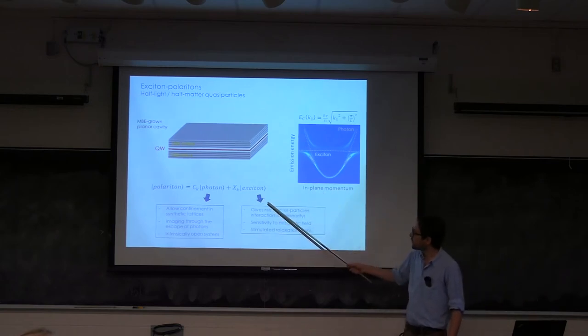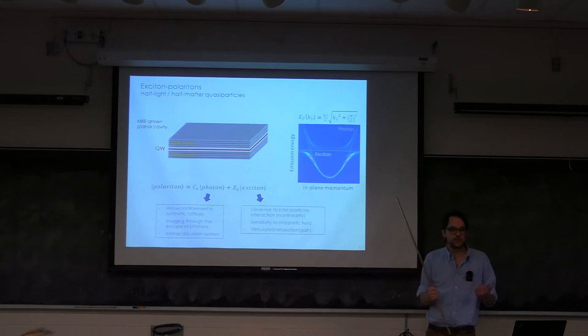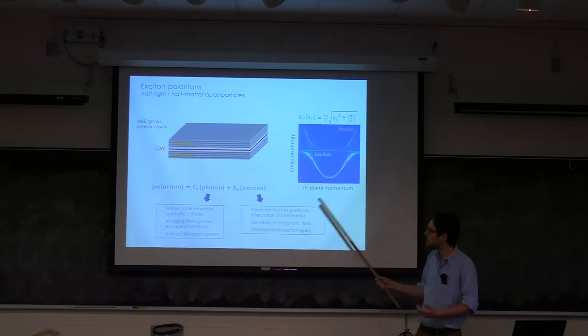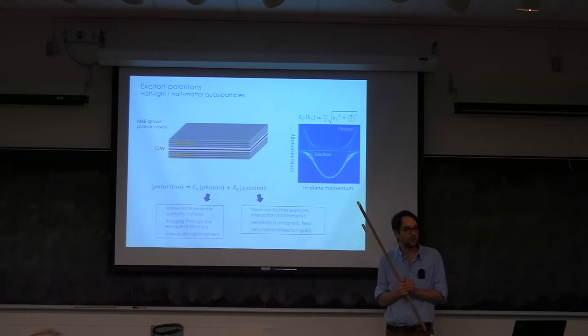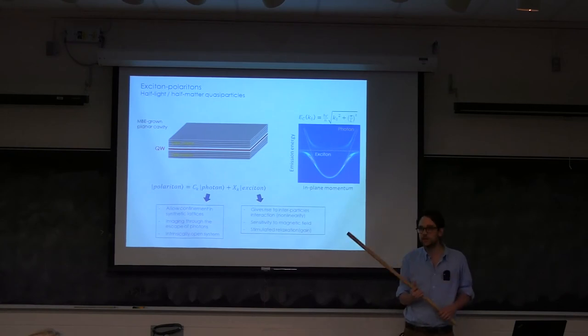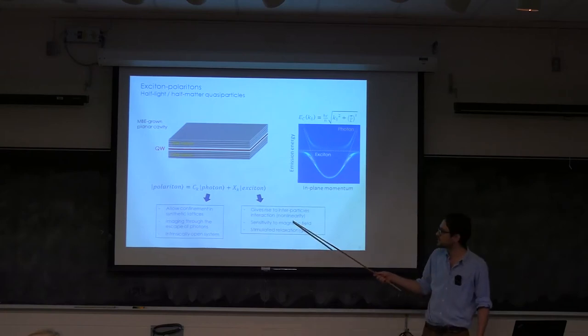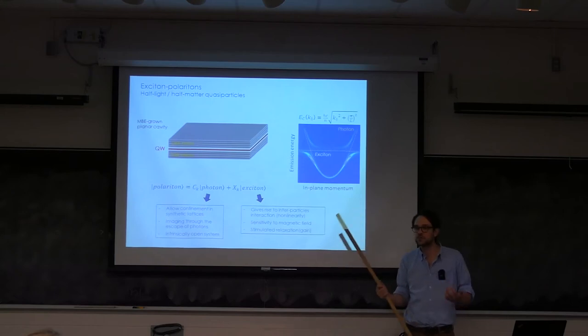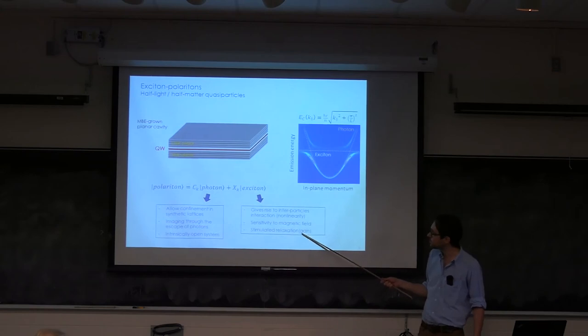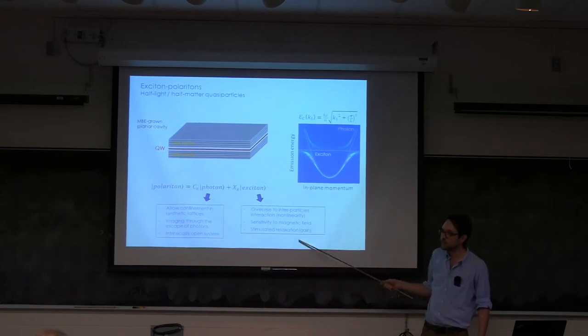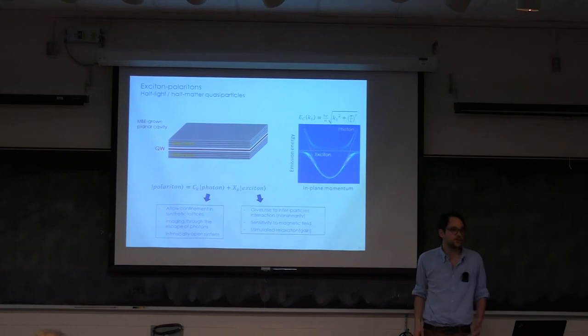On the other hand, the excitonic fraction, so photons usually don't see each other, unless you have a nonlinearity, but excitons do see each other through the Coulomb interactions. And as a result, you can have here a nonlinearity that is really strong, a Kerr-type nonlinearity that is extremely strong for exploring nonlinear phenomena. Also, they're sensitive to magnetic field, so we can put these systems in a magnetic field and start to implement topological phases that, for example, break time reversal symmetry. And also, they would be very important for one of the examples I will show. It's a gain medium. It allows us to enter a lasing regime.